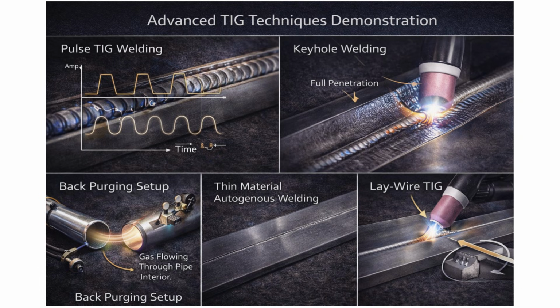Once you've mastered the basics, there are advanced techniques to explore. Pulse TIG uses pulsating current that alternates between high peak amperage and low background amperage. This reduces heat input, minimizes distortion, and allows better control on thin materials. Keyholing is a technique for full penetration welds on pipe or critical joints. You create a small hole through the material and fill it as you progress, ensuring 100% penetration.